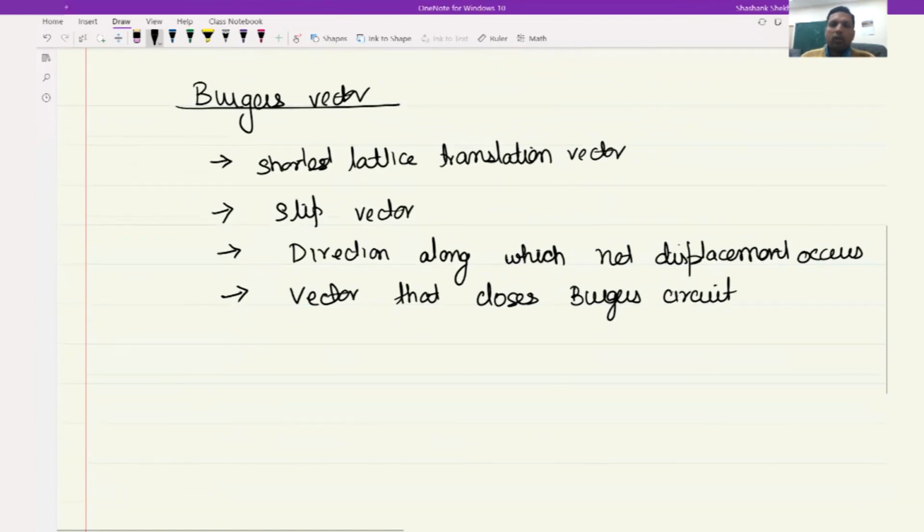Okay, so this is the very basics of dislocation, the edge dislocation and the screw dislocation. And when we looked at edge dislocation, we also realized how it helps reduce the overall theoretical strength, because now the overall slip would take place in small steps instead of shearing all together in one go.